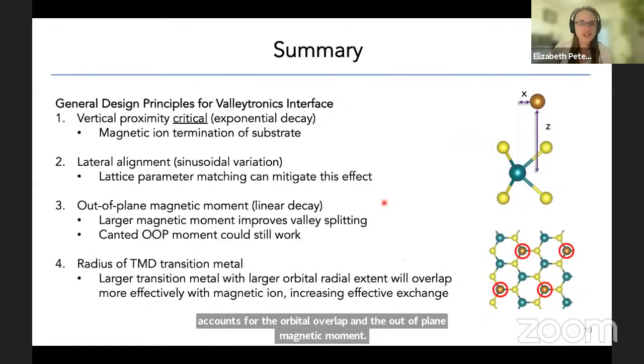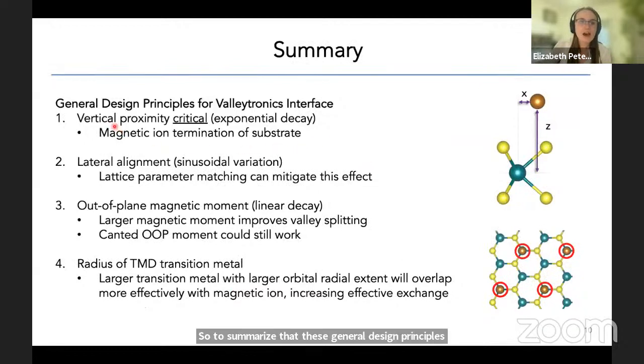So to summarize, these are the general design principles that I've developed. First, vertical proximity is critical because this is an exponential decay. And you can mitigate this by using a magnetic ion to terminate your substrate. The lateral alignment has a sinusoidal variation, and you can mitigate this with lattice parameter matching, which is something that the existing heterostructures that have been explored, like europium sulfide and chromium triiodide, don't have valley splittings as large as what I'm observing. The out-of-plane magnetic moment is a linear decay, and the larger your magnetic moment, the larger your valley splitting is going to be.